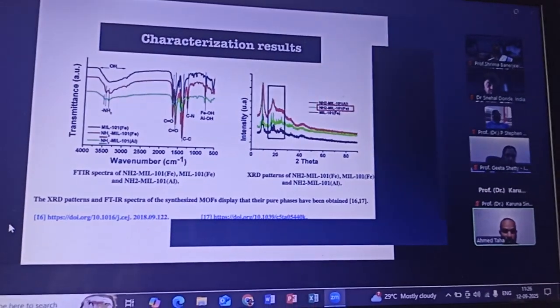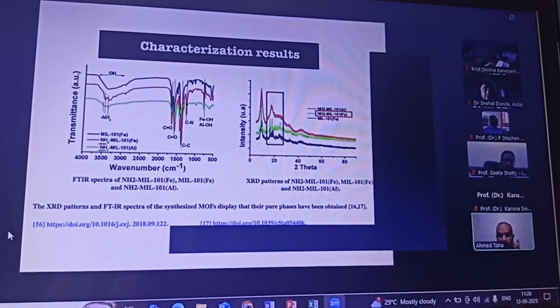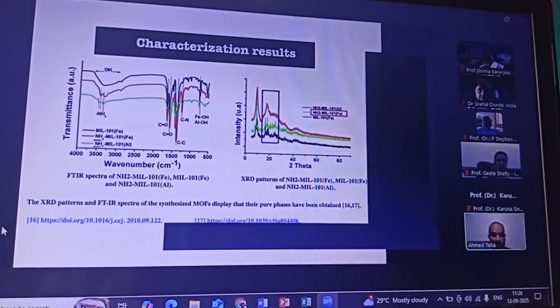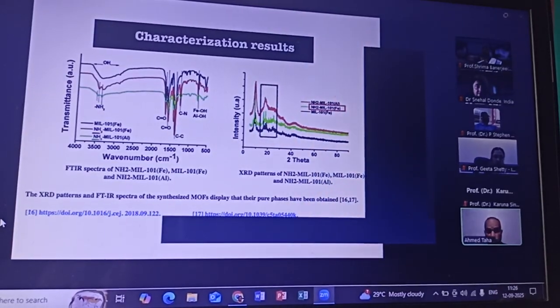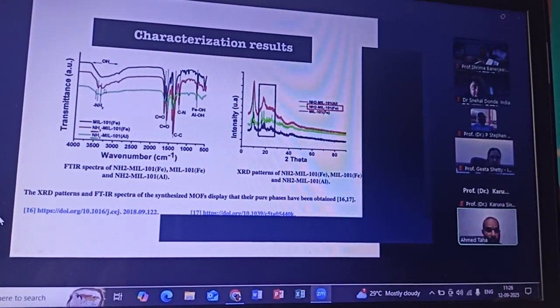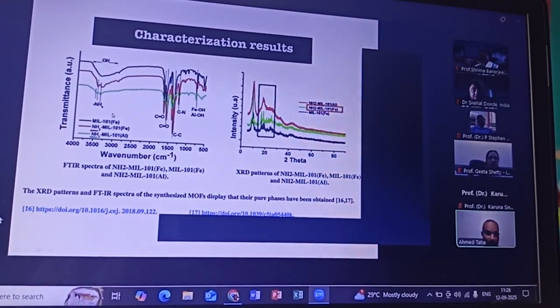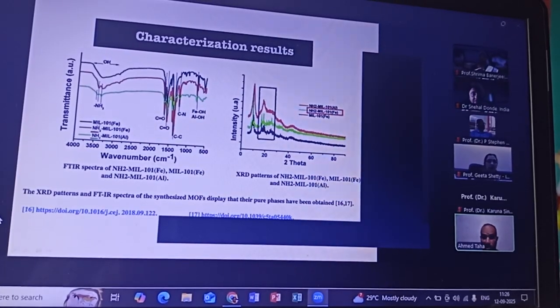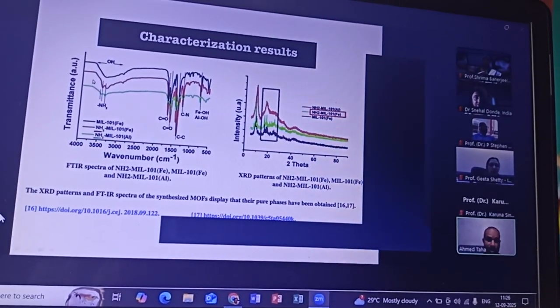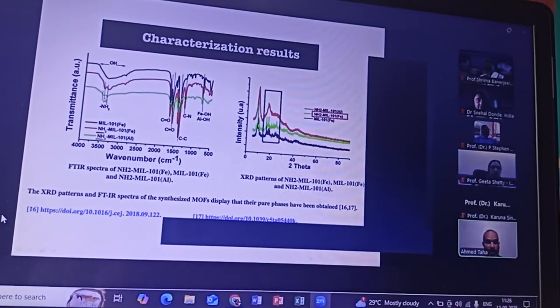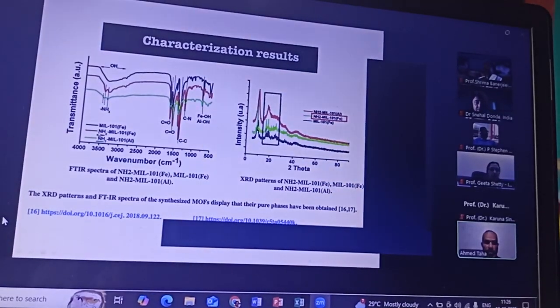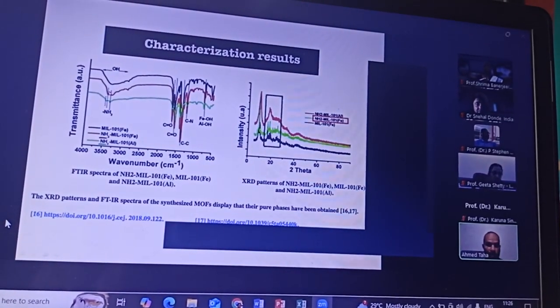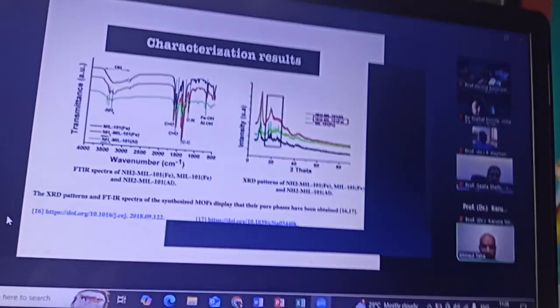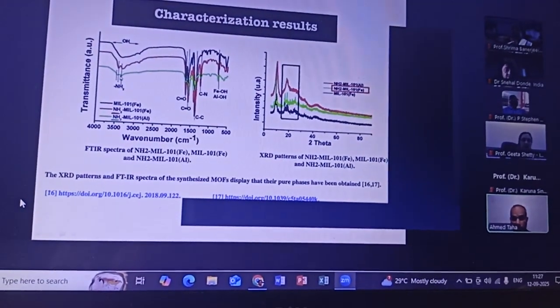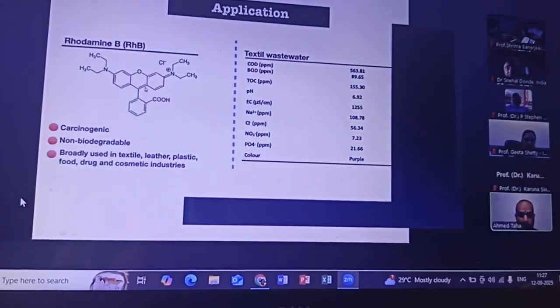So we do the characterization to study our material and to confirm we have the targeted material with the targeted functional groups. We can see, for example, here is the functional group which we have mentioned. We have 2 materials that have the amine functional group, so you can have a reflection here in the FTIR for the functional groups. These are the 2 with the amine group, and this one doesn't have the functional group, so it doesn't reflect in this analysis.